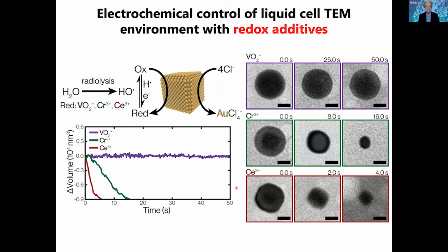We have present inside the liquid cell, this is the work of Ivan Moreno-Hernandez, we add a redox couple. In other words, we add a molecular species, vanadium oxide, VO2 plus, Cr3 plus or cerium 3 plus. We add these cationic species in, and they can be oxidized and reduced inside the liquid cell as a result of their reactions in the presence of the radiolysis environment that creates hydroxyl radicals.